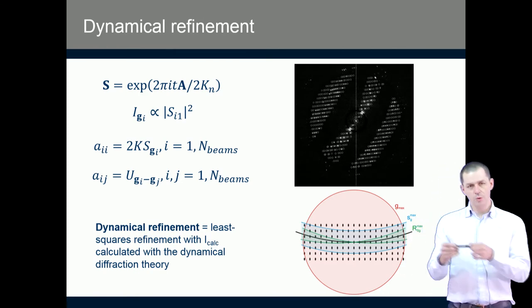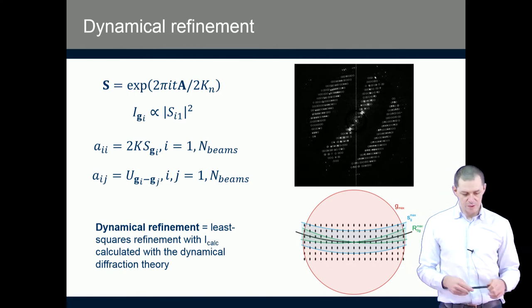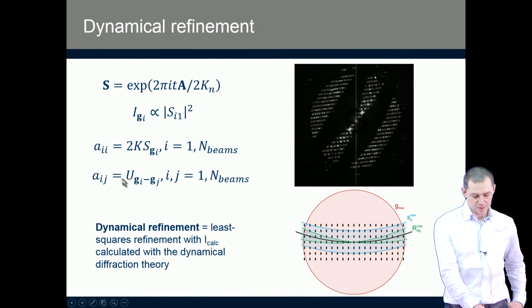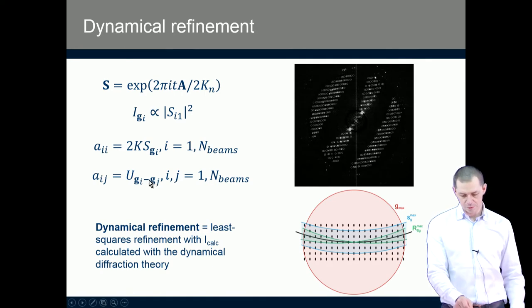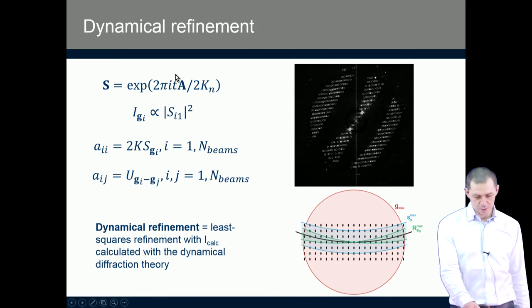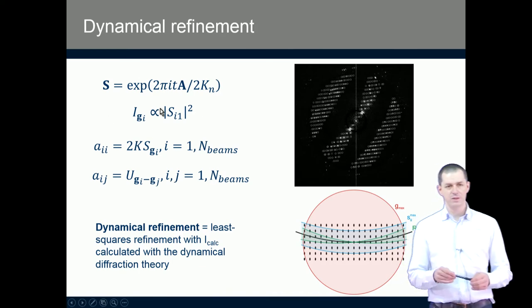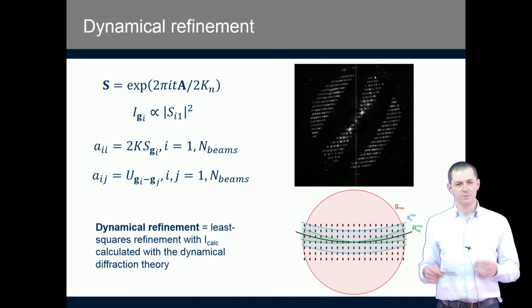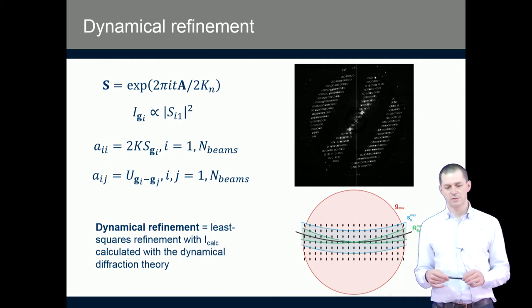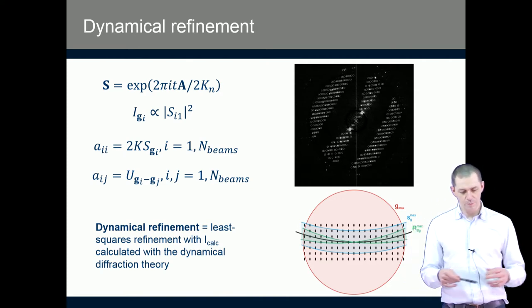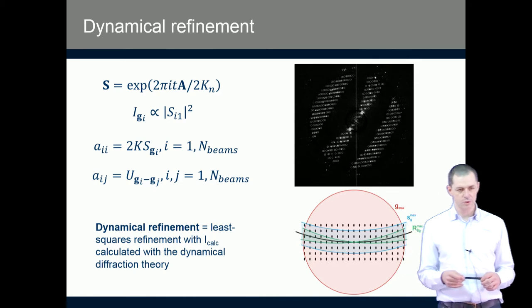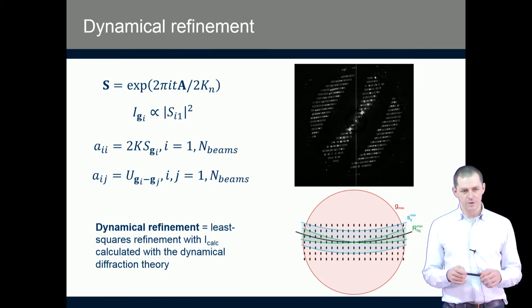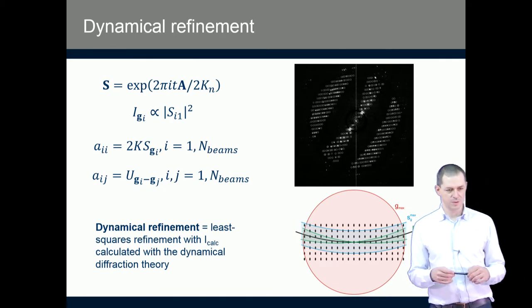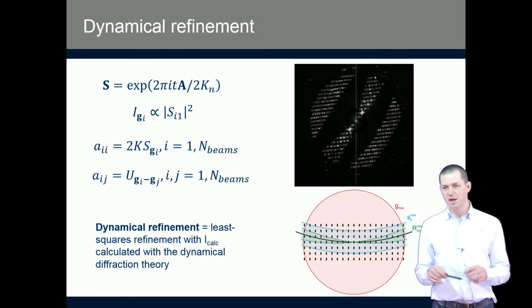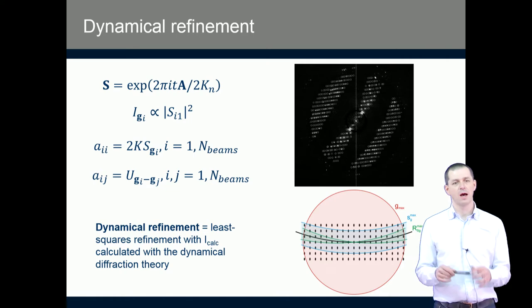Therefore, if we want to simulate it, if we want to do the calculation, we need to build a matrix containing the structure factors of all the reflections in diffraction condition, and then do a calculation which involves exponentiation of a matrix, which is a well-defined mathematical operation, but it requires a certain computing time. So the computing time of this approach is rather long compared to the refinement with kinematical approximation, but it can be done. It's not weeks, it's not days, it's maybe minutes to first hours per cycle.